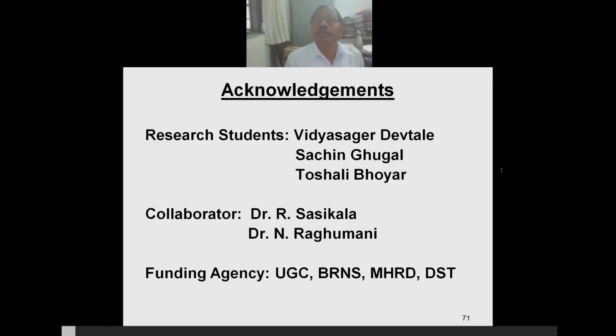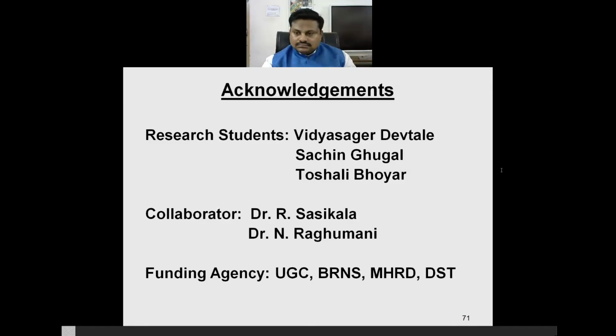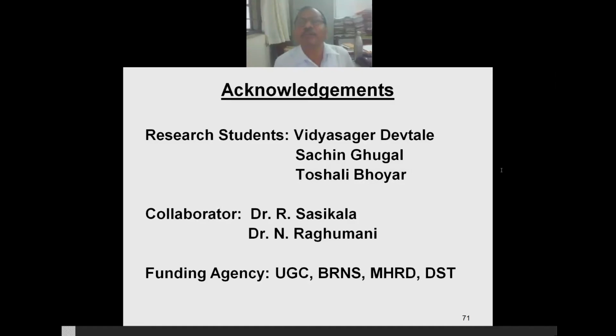For activity enhancement, some modification definitely has to be performed. TiO2 anatase has a band gap of 3.2, rutile is less, 3.0, and there is brookite. And P25 is basically commercial P25, a combination of rutile and anatase.